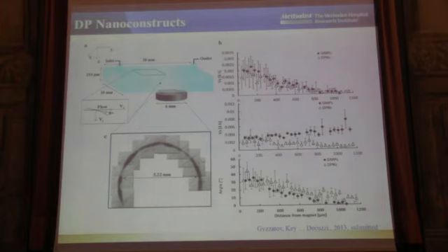But now if you have multiple 5 nanometer particles in a large particle, you can actually use these magnetic forces for driving and guiding these particles wherever you want, even deep into the tissue. Why? Because now you have a lot of iron, made out of 5 nanometer USPIOs that in 1 week, 2 weeks will be completely degraded. So you have both functions simultaneously.